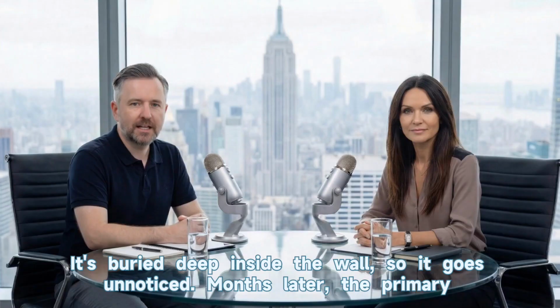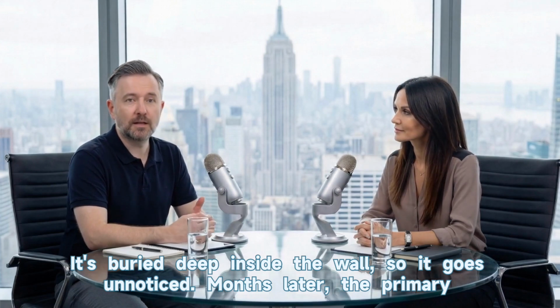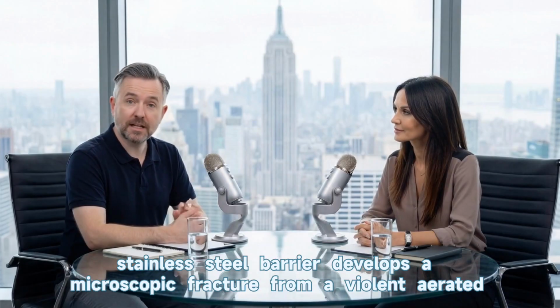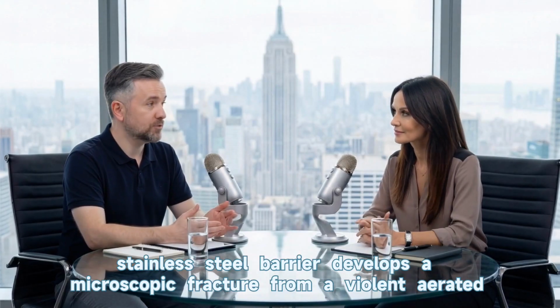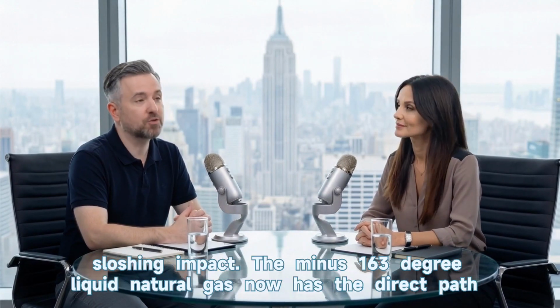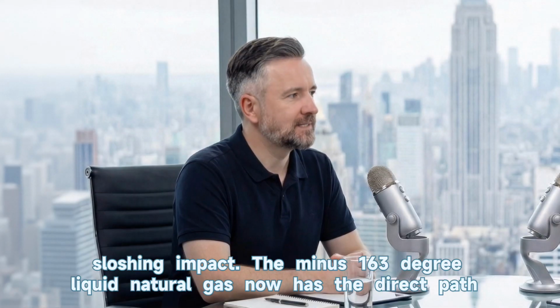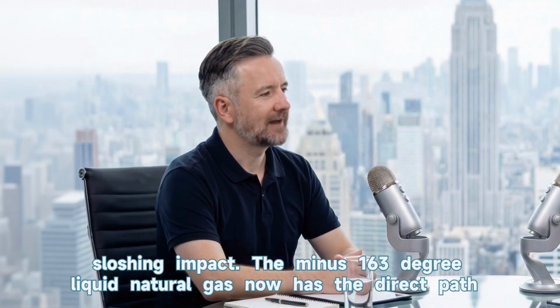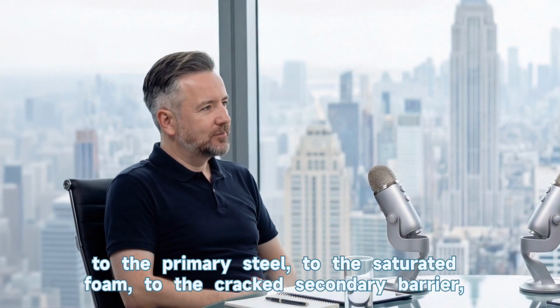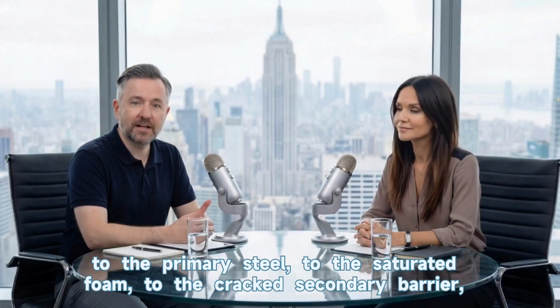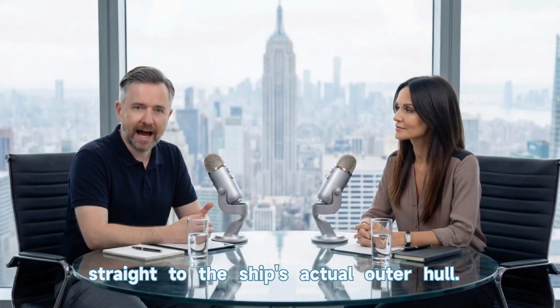Okay. It's buried deep inside the wall, so it goes unnoticed. Months later, the primary stainless steel barrier develops a microscopic fracture from a violent, aerated sloshing impact. The minus 163-degree liquid natural gas now has a direct path through the primary steel, through the saturated foam, through the cracked secondary barrier, straight to the ship's actual outer hull.